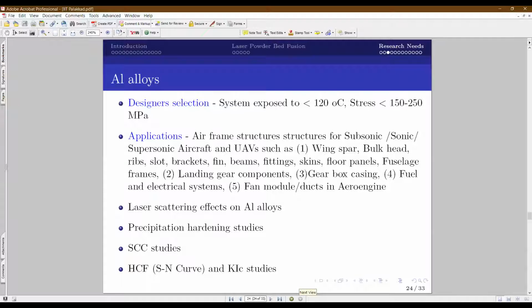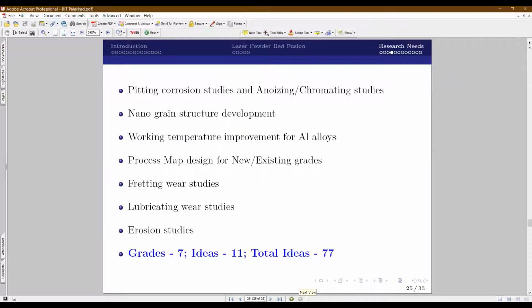And most of the aluminum components which are high load bearing are susceptible to fatigue, mainly high cycle. Understanding high cycle fatigue and fracture toughness is very important. So data generation in this area is the order of the day. Then pitting corrosion is another issue, and the schemes you use to protect aluminum alloys, like anodizing and chromatizing. These area studies are very much needed.